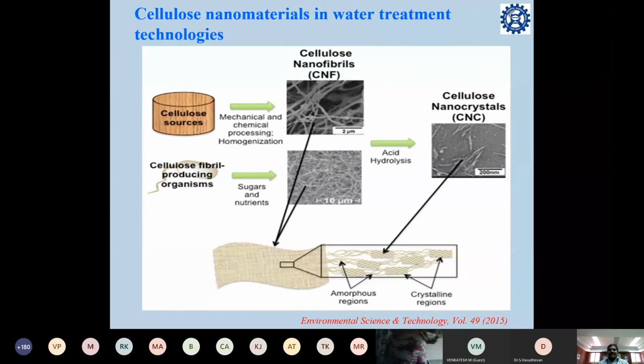We can see the structure. Some images are shown here which have some fiber structure. So these are all cellulose nanofibrils, and these cellulose fibrils can also be produced from cellulose fibril producing organisms. There are some organisms which produce this cellulose. From there also we can extract these cellulose nanofibrils, and then by acid hydrolysis of these cellulose nanofibrils we can make cellulose nanocrystals, and finally these cellulose nanocrystals can be made into membranes. These membranes have both amorphous regions and crystalline regions. That means when the fibers are packed regularly in a compact manner, it causes crystalline regions, and if you take a single fiber in random orientation, it will be an amorphous region. So when you make a membrane from the cellulose nanofibrils, it contains both amorphous as well as crystalline regions.